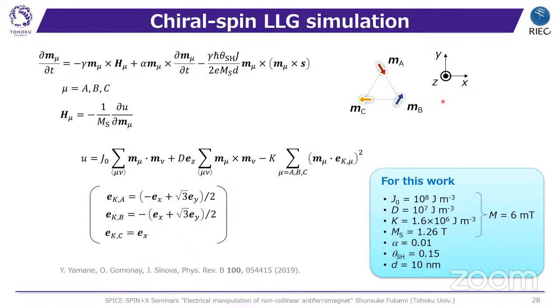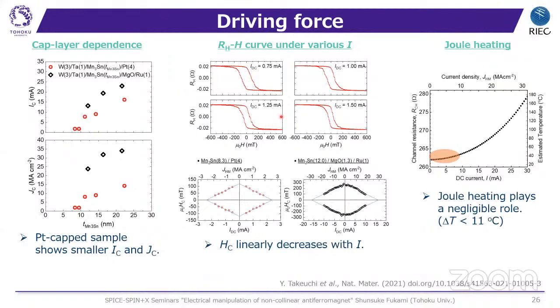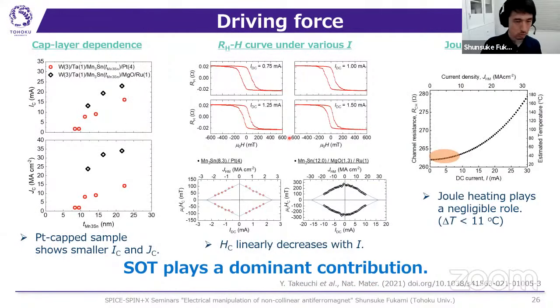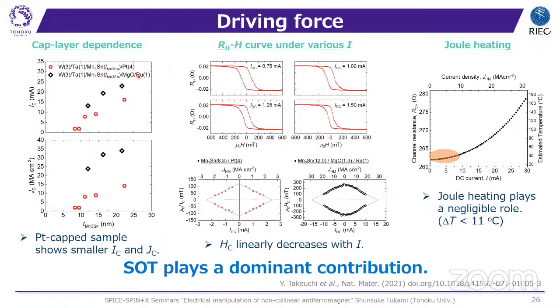Okay. And at last, this question about different substrates, metal and non-metal. The response is different. I think it was slide 26. So actually, we use the MgO substrate. The order of the stack from the substrate side is tungsten, tantalum, manganese tin, and platinum. This is the cap side. But it's sitting on magnesium oxide, and this is an insulator. So the effective interaction between magnetic atoms via the substrate is very different. In platinum, you have conduction electrons, while in oxide you don't, which means it's a different system.